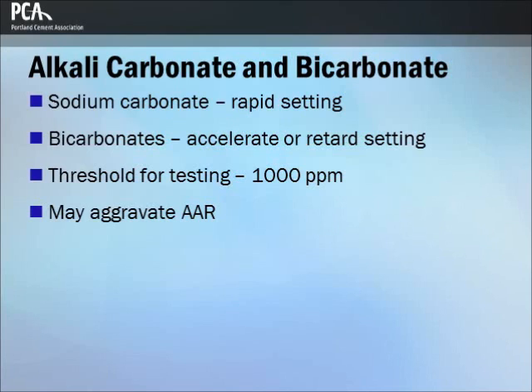Carbonates and bicarbonates of sodium and potassium have varying effects on the setting time of different cements. Sodium carbonate can cause very rapid setting. Bicarbonates can either accelerate or retard the set depending on the chemistry of the cement used in the concrete. In large concentrations, these salts can materially reduce concrete strength. When the sum of the dissolved salts exceeds 1,000 ppm, tests for their effect on setting time and 28-day strength should be made. The possibility of aggravated alkali-aggregate reactions should also be considered.